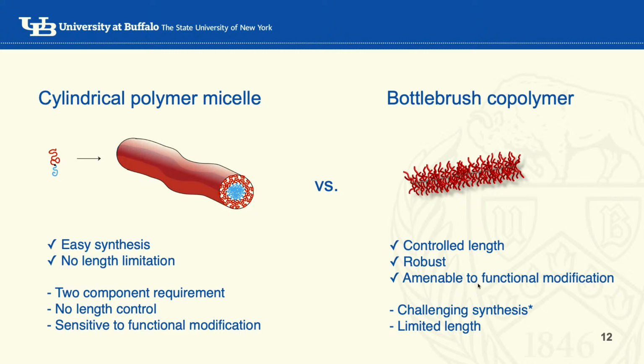Yes, the self-assembly in water is a bit more complicated. There are hydrophobic and hydrophilic groups, so there are van der Waals interactions, but there's no hydrogen bonding, whereas there is hydrogen bonding in water. Typically when hydrophobic domains separate from water, it's actually an entropic process, not enthalpic, because of the structure of water molecules around hydrophobic groups. But you don't need to have strong interactions here. Any weak interaction will do because each polymer has many repeat units, and so even small interactions between repeat units add up to a very large delta H.